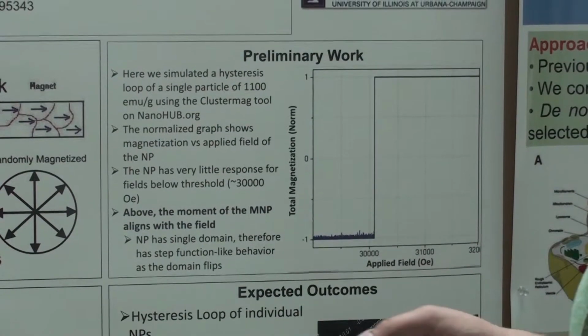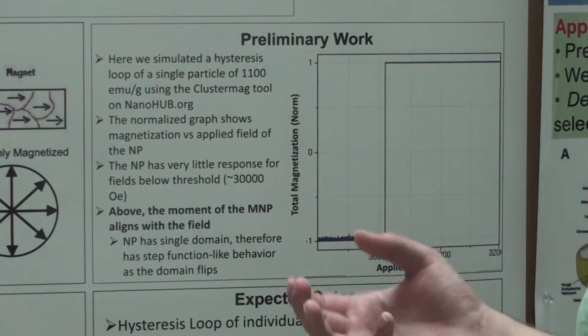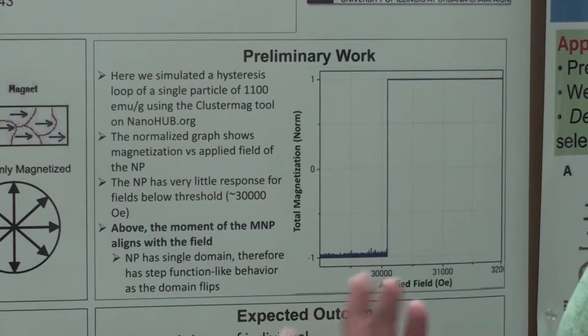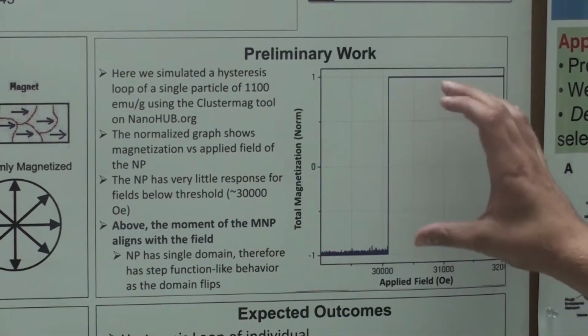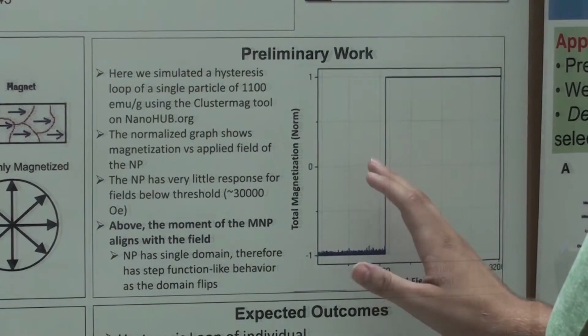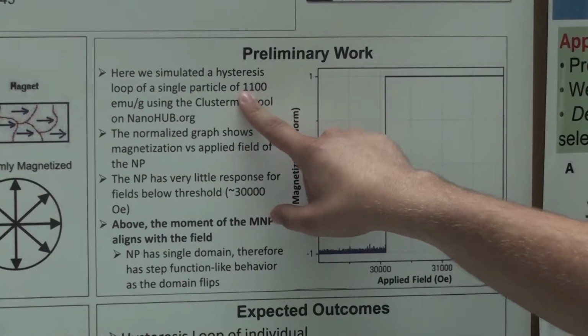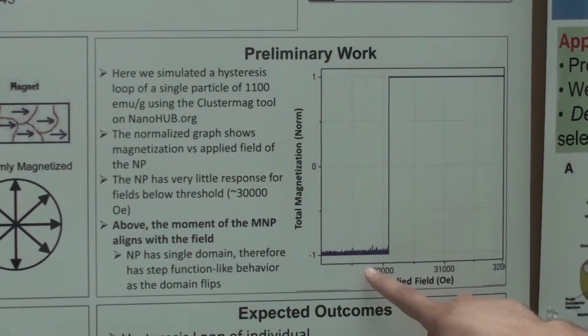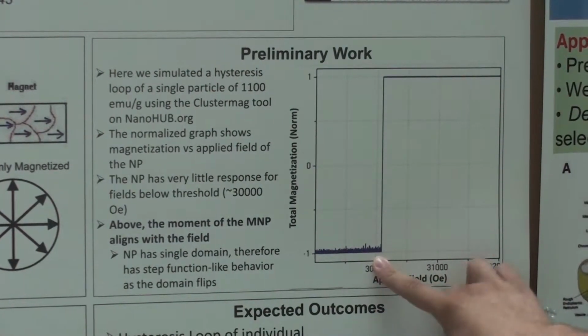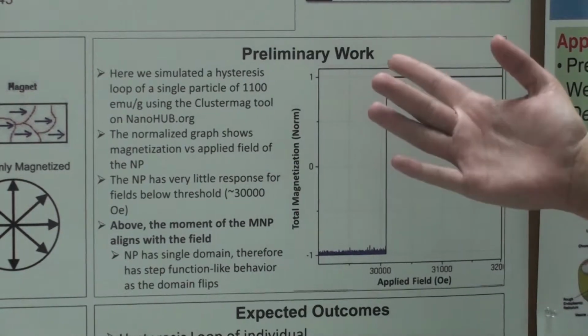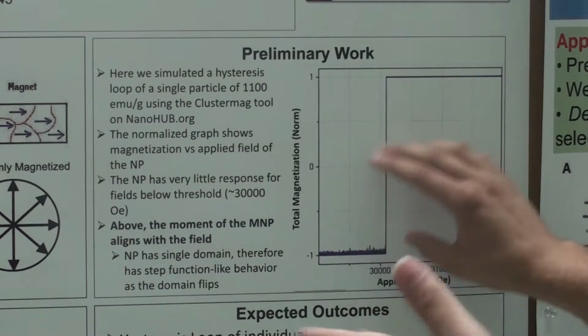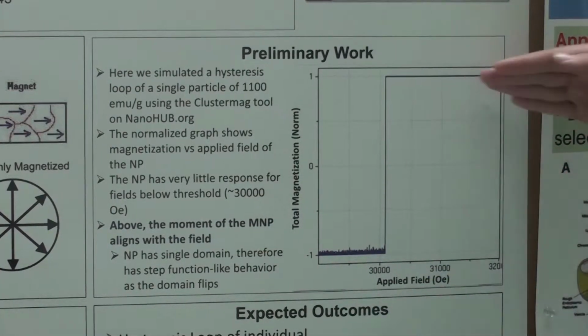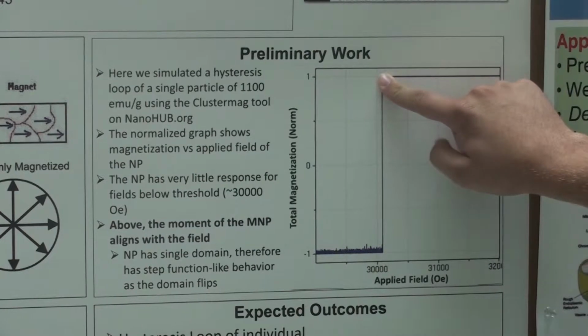So there's another tool on NanoHub called ClusterMag, and this allows you to simulate the hysteresis loop and magnetic moment of any magnetic nanoparticle. So this particle has 1100 emu per gram. As you apply a field at around 30,000, the magnetic moment flips. It's like a step function. It has no response until it does respond. And then coming back down, it responds at the exact same threshold,